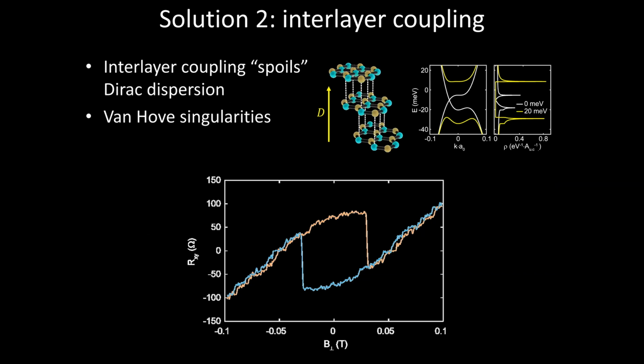Okay, then you need to make interactions strong. You need to somehow reduce the bandwidth, or at any rate increase the density of states. And it turns out the way to do that is generically interlayer coupling. So this massless Dirac dispersion is immediately spoiled as soon as you have 2 layers of graphene. And it turns out not to matter at all how you put that second layer, you're always going to find magnetism somewhere. That's something that we've learned in the last couple of years.